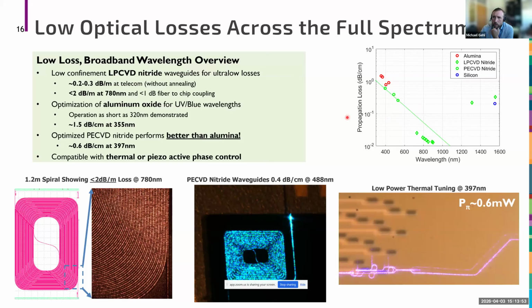And then, just to mention, all of these wavelengths are tunable through either thermal or piezo tuning. On the bottom right here, I'm just showing an example of one of our thermal phase shifters where we can tune the silicon nitride Mach-Zehnder interferometer with very low power, only about 0.6 milliwatts required to get a pi phase shift.